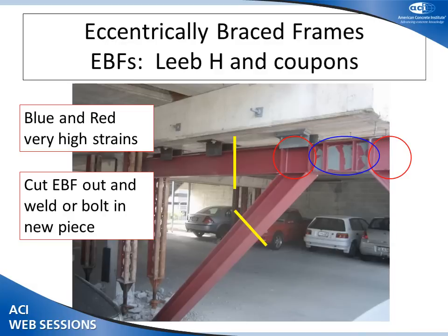Just the same shot again. These zones were measured using Leeb Hardness tests and water jet cut coupons, not heat cut coupons. And we found that the strains there were right at the end of what was left in those particular elements. We also found that the high strains actually worked out along the header and down the legs as well. The solution was to cut those pieces out and replace them in their entirety over the building.